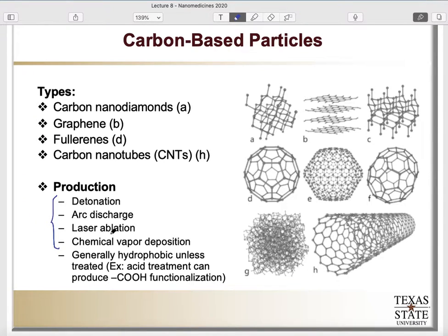Then the carbon condenses, producing the carbon nanostructure. And you can utilize different kinds of catalysts in those reactions in order to provide the shape to the material. In arc discharge, you're actually able to modulate the pressure of the gas or the current in order to control the shape of the resulting nanostructure.